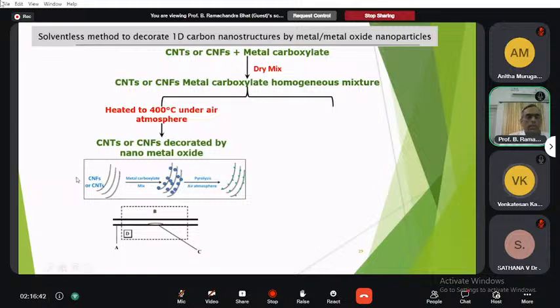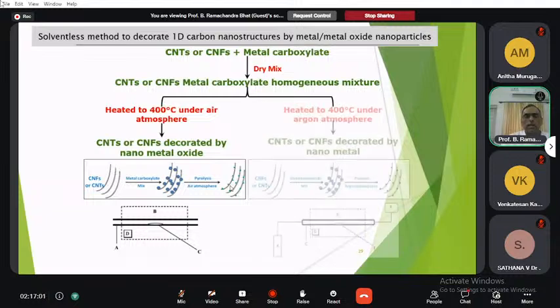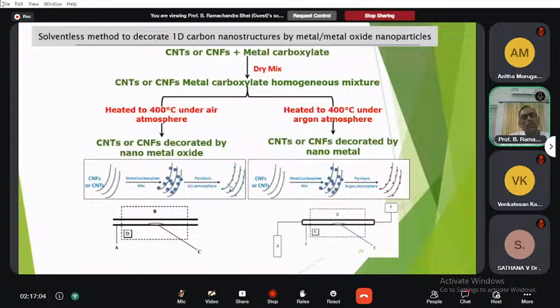You can see the slide here, CNF or a CNT. So on mixing and heating around 400 degrees Celsius, on pyrolysis under air atmosphere, the metal oxide is decorated on the CNT or CNF. But on the other hand, if you heat at around 400 degrees Celsius under argon atmosphere or inert atmosphere, you can see that only the metal nanoparticles are getting decorated.